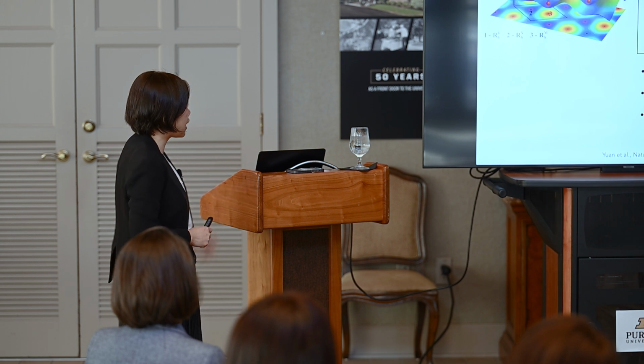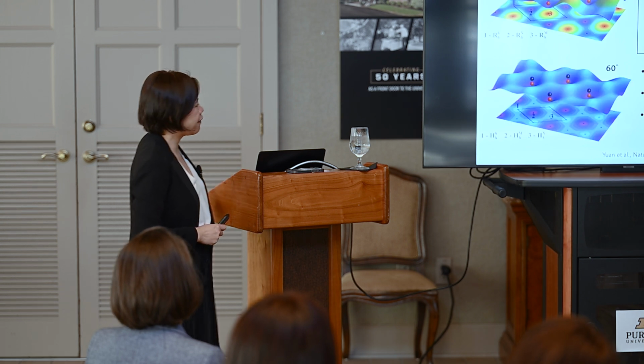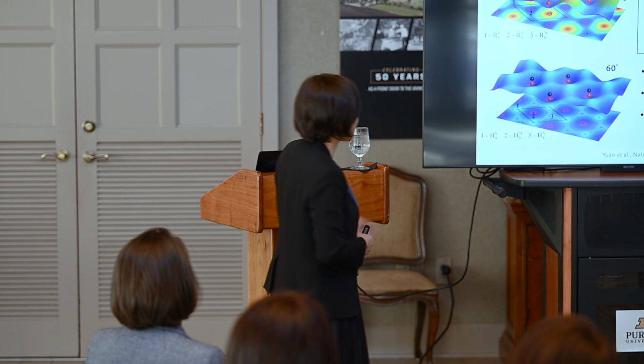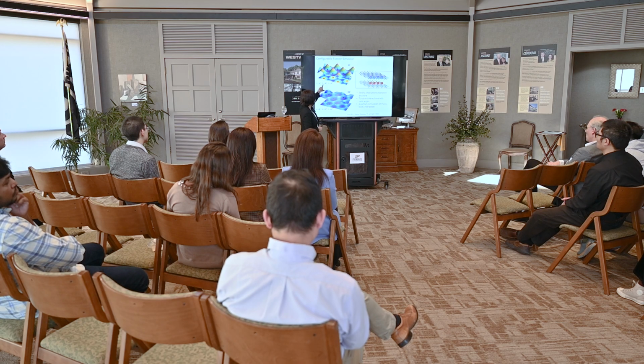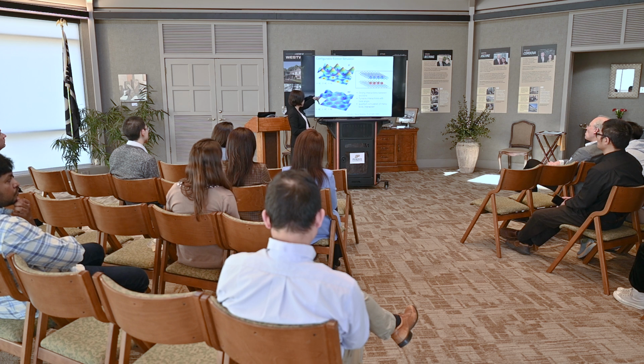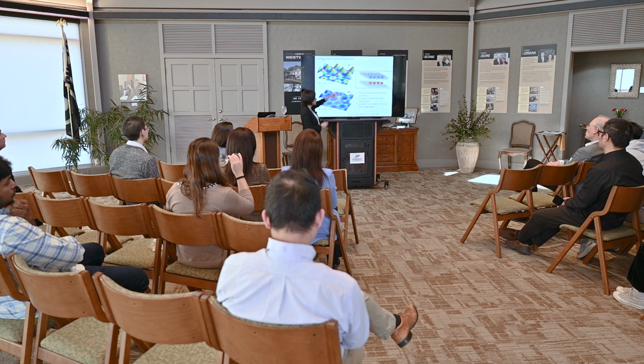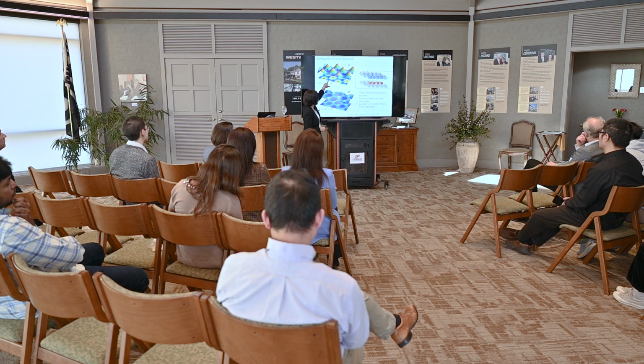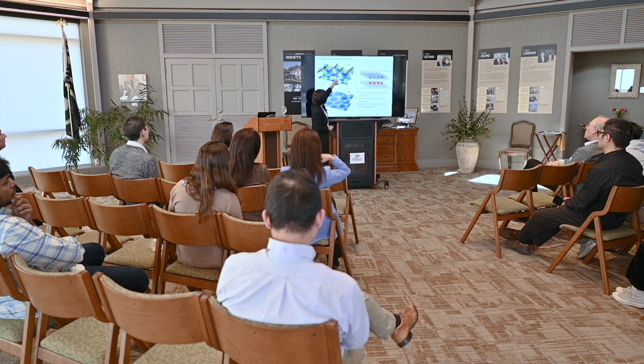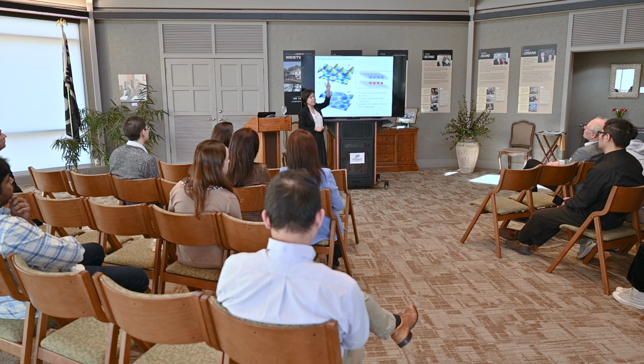In this case, this is some simulation that we did in the past with our collaborator. If we twist these two layers, tungsten disulfide and tungsten diselenide, and have a 0-degree twist between them, the excitons would reside at these known locations, and they would have a relatively high barrier between them.